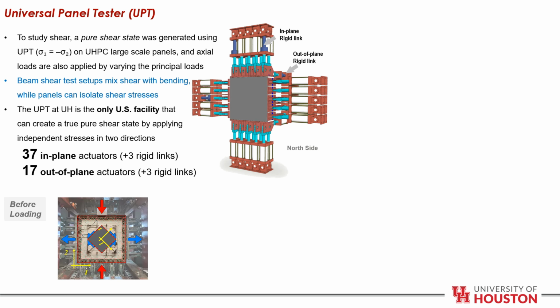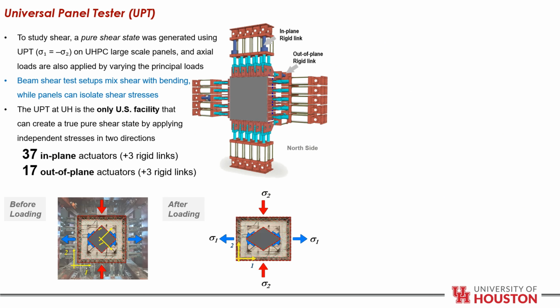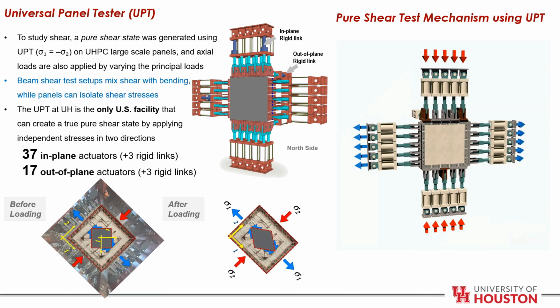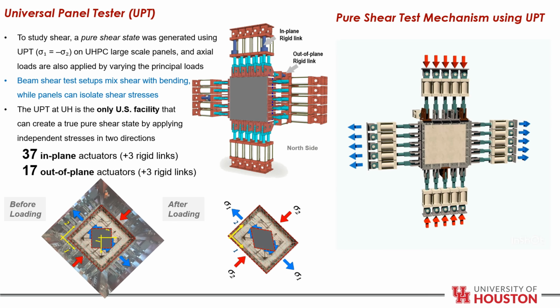The test mechanism follows the Mohr circle, where the biaxial loads are applied in the principal directions, and the element under shear test is rotated at 45 degrees. So as we can see, after loading, the element will experience shear stresses oriented at 45 degrees. And here's a video demonstrating the test.